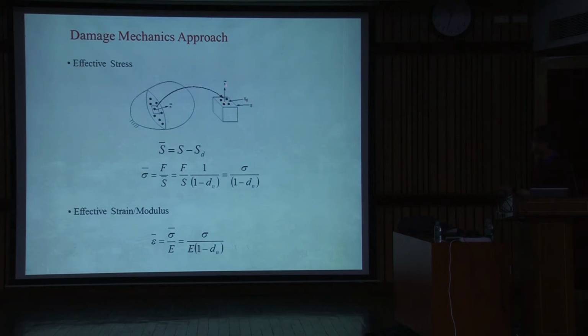So whatever load is taken or resisted by the surface normal to this will be the total area minus this damaged area. This is the effective area, and the stress on it is called the effective stress. This is your actual load and this is the effective area. So you make some adjustment: you take S common, and this S bar is represented as S times 1 minus SD by S. SD is nothing but your damaged area upon total area. This ratio is defined as the damage indicator.